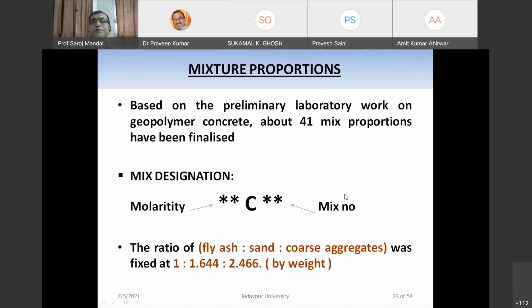Now, based on some preliminary laboratory work, we have about 41 mixes, and we have designated the mixes like this. On the left hand side we put the molarity, and the right one is the mix number. Suppose we say 8C2, that means the mix number is 2 and 8 is the 8 molar mix. And the ratio of fly ash, sand and coarse aggregate was fixed for all the 41 mixes, 1:1.644:2.466. This has been done after so many trials.